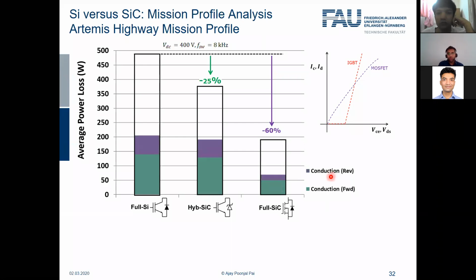Then the losses due to conduction in the reverse direction, which is basically the power loss of the diode. Here we see that the silicon carbide diode has slightly higher losses than the silicon diode. This is because silicon carbide Schottky diodes have a larger voltage drop compared to the silicon diode. They're not so good in terms of conduction, and this is coming actually because of the higher band gap. But anyway, it's a trade-off.